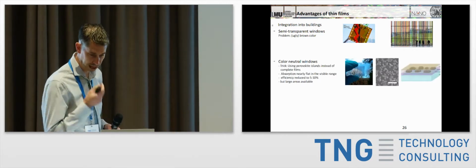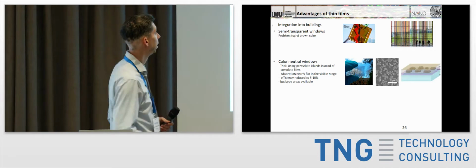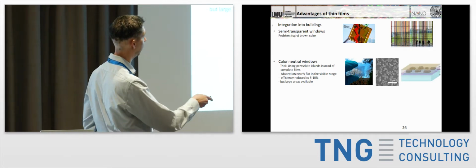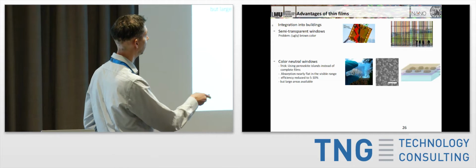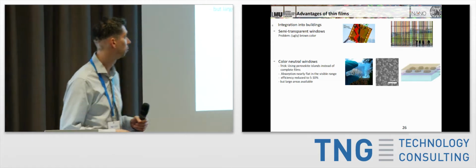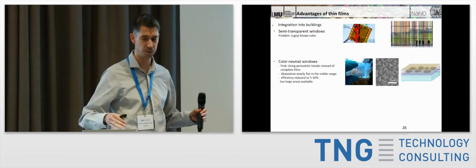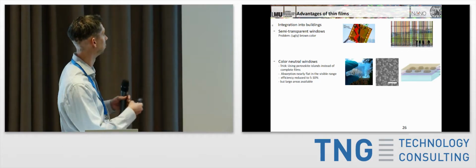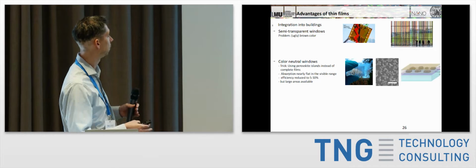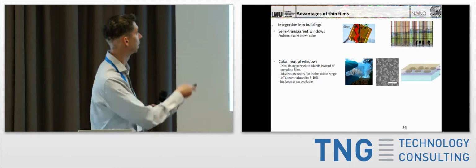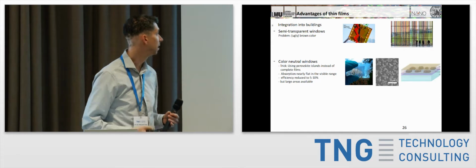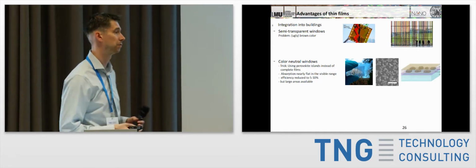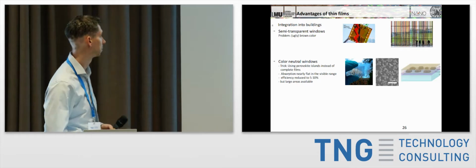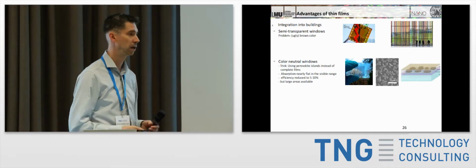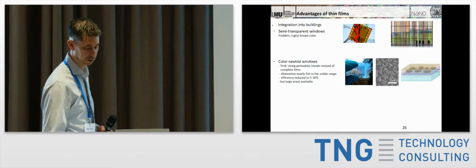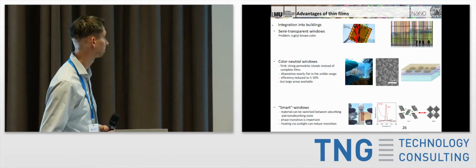And so one of the ideas that somebody came up with was actually producing color-neutral windows. The way that they did this was, instead of making a thin film of perovskite, a continuous film, they developed islands. And through this sort of island formation, they were able to change the absorption from deep to only partial. And so the absorption spectrum itself is nearly flat throughout the entire visible range. So instead of having a dark brown, you essentially just have a sort of gray. Obviously, it reduces the efficiency to only about 5 to 10%, but if you think about the areas that you have on buildings for windows, especially skyscrapers, you have huge areas available, and so that can more than compensate the loss in efficiency.